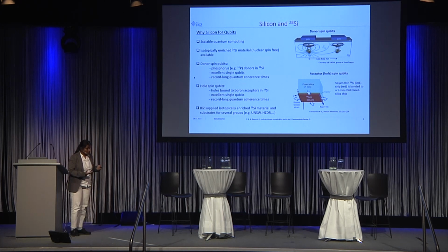Because we are only the producers of the materials and we don't make the quantum devices ourselves, our collaborators do that. There is a possibility to make donor qubits on silicon or hole spin qubits. The donor qubits you can make by implanting phosphorus, as Peter told. You can make an ion implantation in the material, and these phosphorus donors act as qubits in silicon, and also in isotopically purified silicon-28. The isotopically enriched material gives very high efficiency for your qubits, and also a very long coherence time. The other possibility is to dope boron in silicon or in silicon-28 enriched material, so that these holes which are bound to the boron acceptors give a very long coherence time in the qubit.